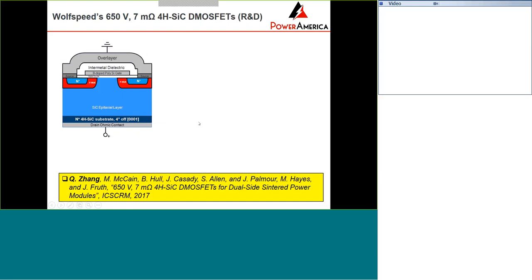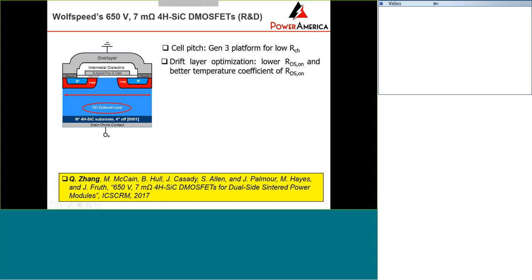Last year, Wolfspeed demonstrated low voltage devices at 650 volts. That chip used the Gen 3 platform, and the cell pitch was optimized for low resistance. Of course, for these low voltage devices, the drift layer doping is higher than the number used for high voltage devices. It has been optimized to reduce the resistance component from the drift layer. Studies have also shown that the drift layer doping concentration largely affects the temperature coefficient of the resistance. The higher the doping concentration of the drift layer, the lower the temperature coefficient of the on-resistance.